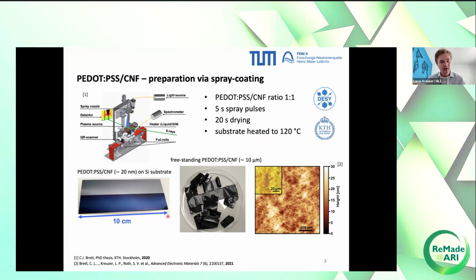Or if you are willing to invest a little bit more time and material, of course, you can also spray coat thicker films. So these are around 10 microns. And you can even detach them from the silicon substrate once you cross a critical film thickness. I am not sure about the film thickness, but once they are thick enough, you can detach them from the substrate, and then you end up with these freestanding PEDOT:PSS, CNF films. Also macroscopic in size. I think the length here would be around 7 centimeters, but on a nanoscale, still homogeneously mixed.